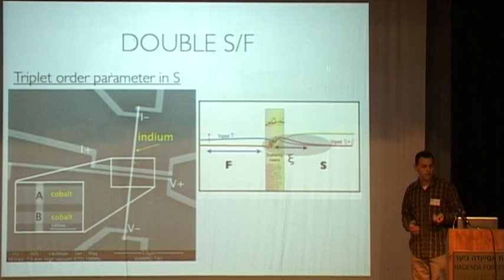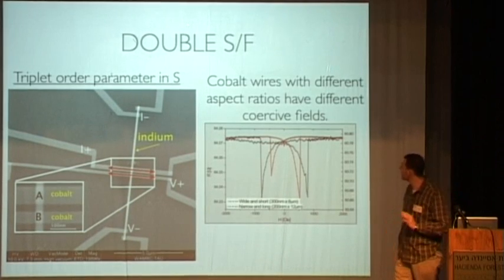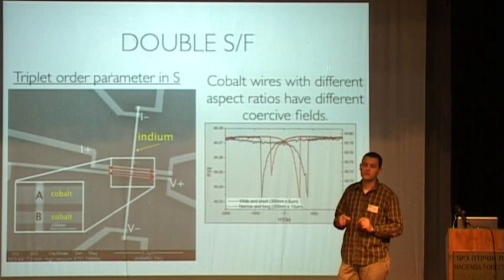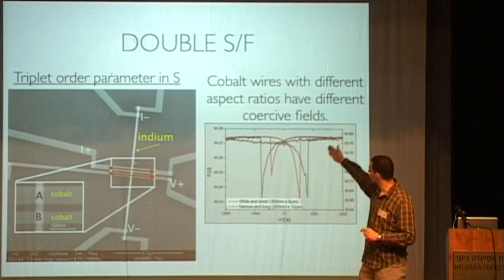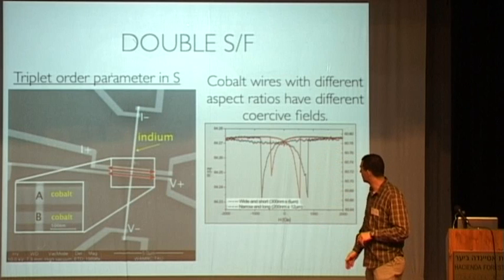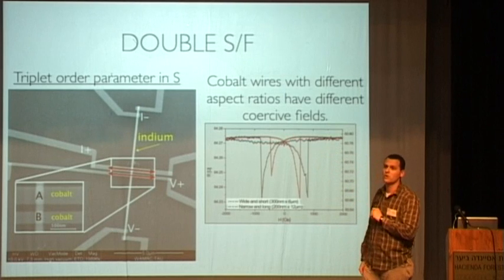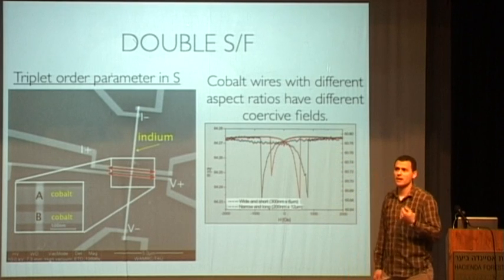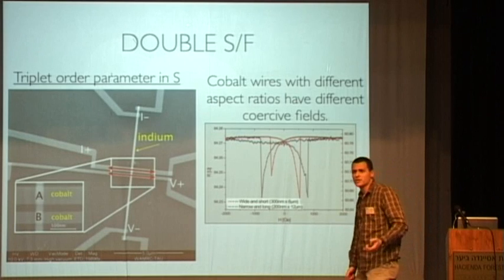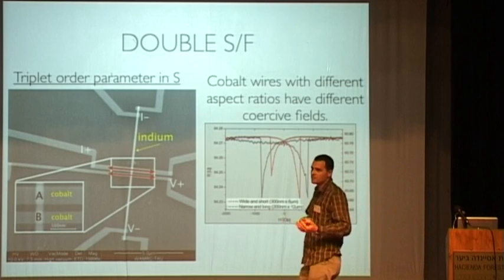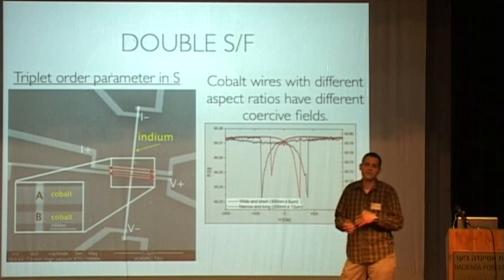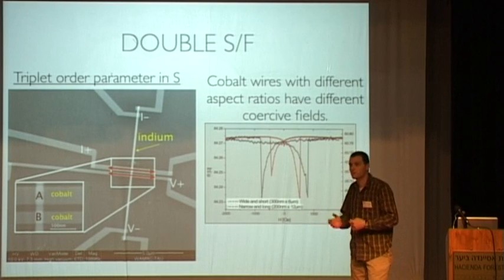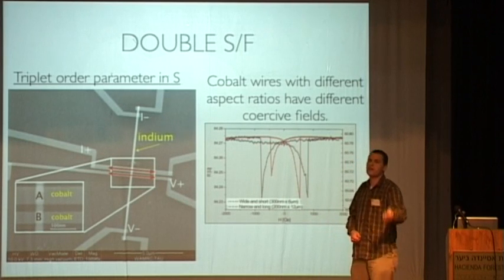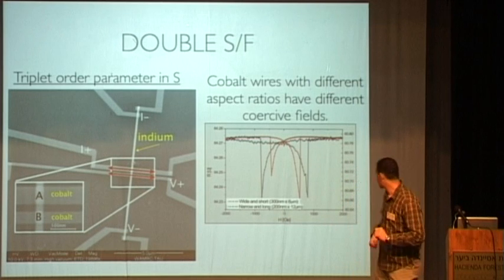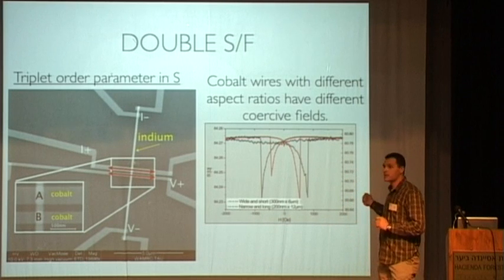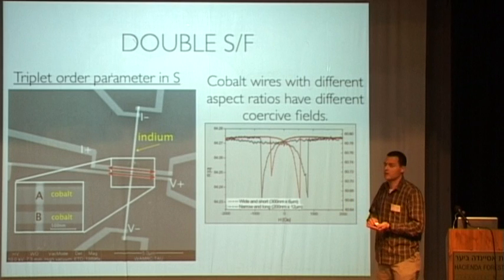And for that, what we do is we fabricate two junctions close by. This is indium, vertical indium, connected by two horizontal cobalt wires. And the cobalt wires have different aspect ratios, so we can manipulate them. Different aspect ratios mean they have different switching fields, because we want to switch them to this direction and to that direction. So we can tune the system into parallel configuration and anti-parallel configuration.